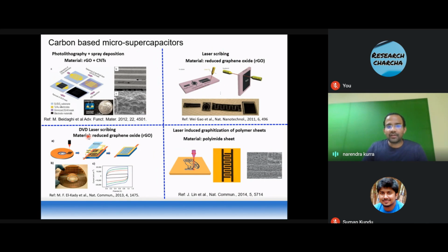And here, DVD laser scribing is a very scalable and cost-effective process to make micro supercapacitors. In this work, many graphene-based micro supercapacitors have been demonstrated using a simple compact disc or digital video disc laser scribing technique. This is a highly scalable approach, but the resolution is very poor in such micro supercapacitors.